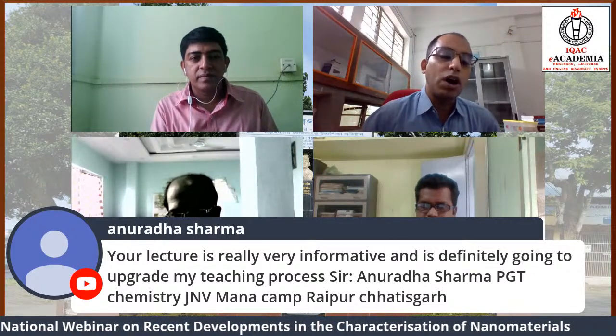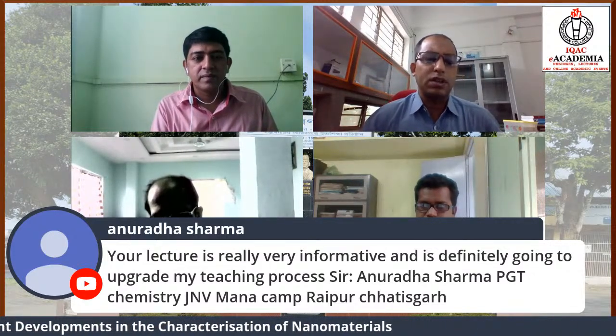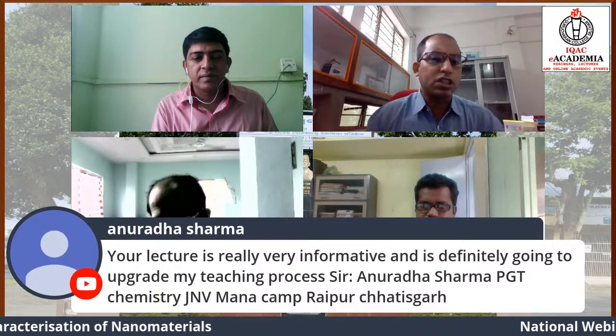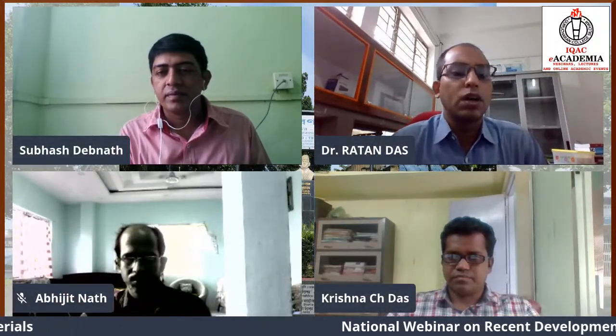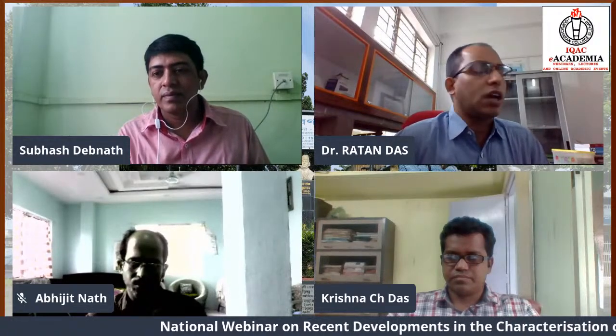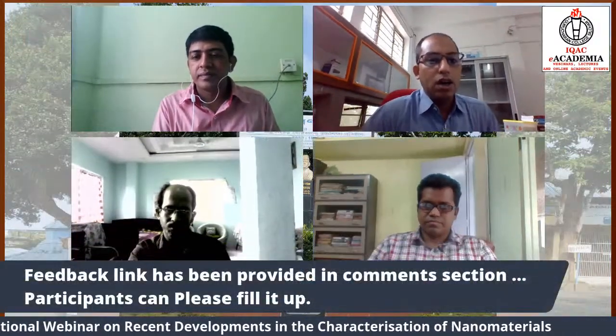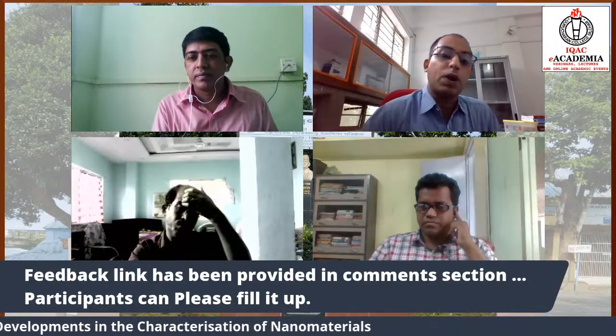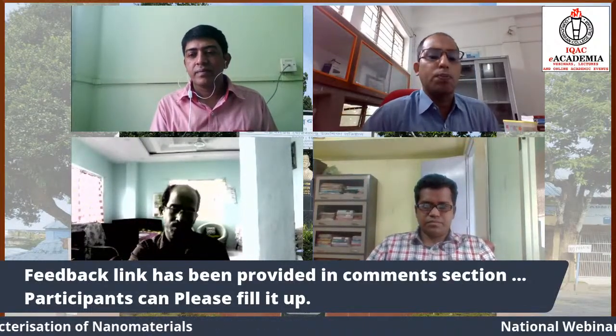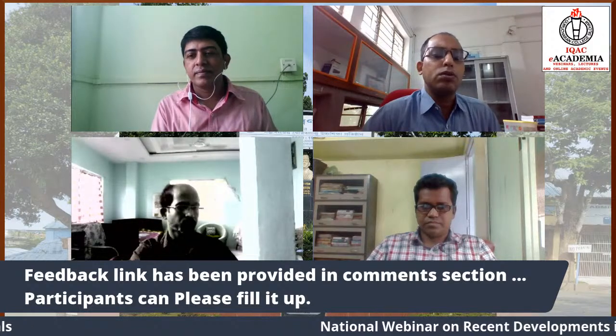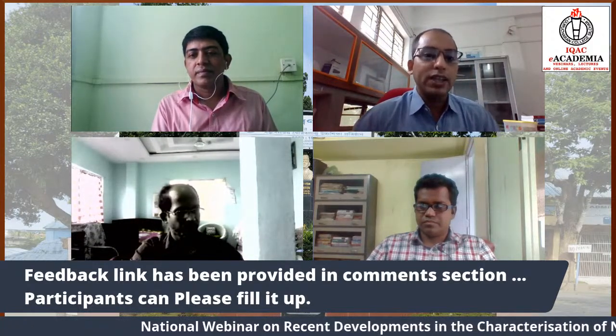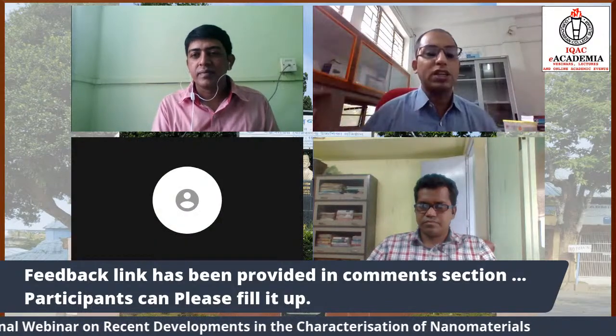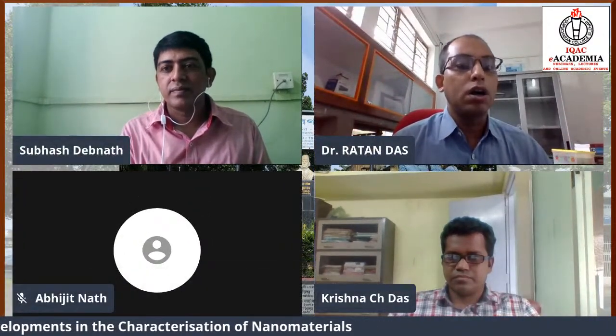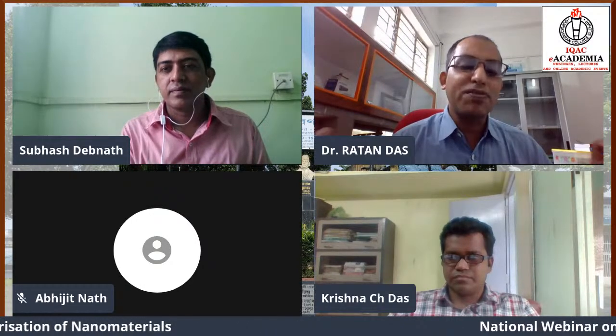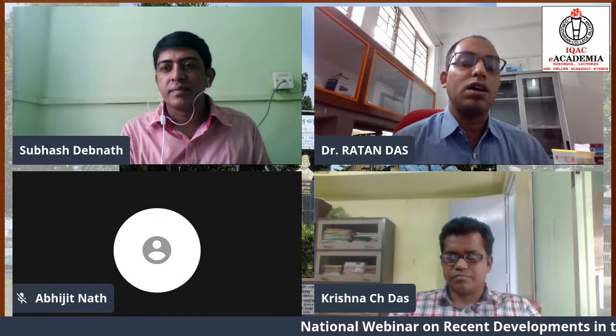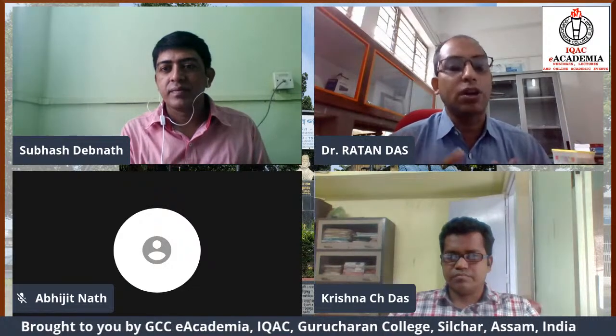And Raman does not give us any visual structure of the surface. Sometimes Raman also gives us strain. Raman gives us the vibrational spectra of that particular sample. So many things we can obtain from the Raman. But generally, I want to say that for morphological analysis, for surface structure analysis, as a whole, the bigger surface, we will use the AFM or a scanning electron microscope. But FTIR study is used for the chemical bonding of some ligand to the nanoparticle surface.